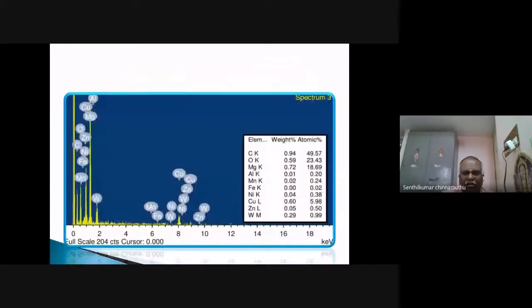And the EDX analysis shows that the parent material as well as the tool material is deposited on the surface. See that aluminum, magnesium, zinc, nickel, ferrous, manganese, all are present, all are in the parent material. The copper is deposited on the surface of the workpiece due to dielectric cracking, and along with the copper, tungsten carbide is deposited. See here, the tungsten carbide deposit is 0.29 compared to semi-sintered. The sintered has a very small amount of tungsten deposited, because in semi-sintered, with more energy, more tungsten carbide is deposited on the surface, whereas in the case of sintered, very little tungsten is deposited because it resembles a solid tool. The bonding within the tool is very high, whereas in the case of semi-sintered, the bonding between the copper and tungsten is very weak, so that more amount of material is deposited on the semi-sintered electrode.